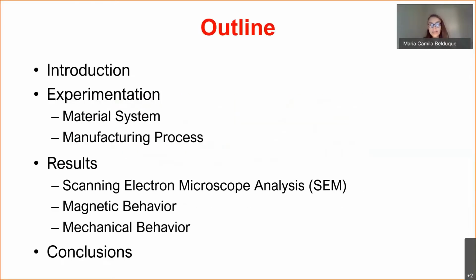So this is our outline. After a brief introduction, we are going to describe our materials, which are strontium ferrite and PA12, and how we manufacture filament composites via single screw and twin screw extrusion. In the results sections, we are going to compare the distribution of particles via scanning electron microscope and the magnetic properties measured with a vibrating sample magnetometer on both the filaments and the 3D printed samples deposited with and without an external magnetic field. We also tested the flexural behavior on the 3D printed samples according to ASTM D790.